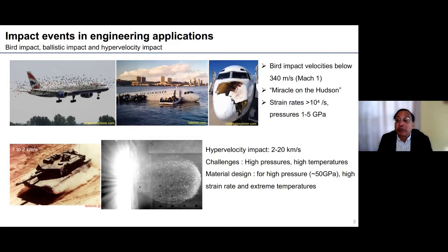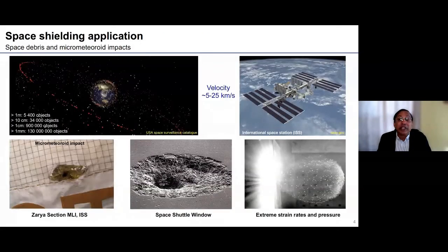To model such problems, we need accurate constitutive models. And these constitutive models, as we know, are a function of strain rate, temperature, and other variables. Typically, we don't consider pressure at relatively nominal pressures, say in most metals in the order of 5 to 10 GPa. These pressure effects are not important, as we know from our work. But what we are interested in is very, very high pressures. And as I mentioned, one of the applications is hypervelocity impact.